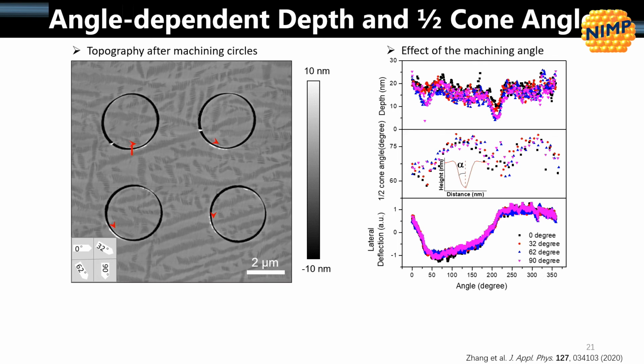And this can be improved just by using a stiffer lever. If you improve the stiffness so that the lateral stiffness is higher, more comparable to the normal stiffness, the tip won't twist as it's going around and carving this structure. But for the rest of the work, we only carve in that direction. So we're going to carve a very small structure, and what we do is take the sample and rotate it, so all the lines we draw, all the cuts, are with this 0 degree scan.